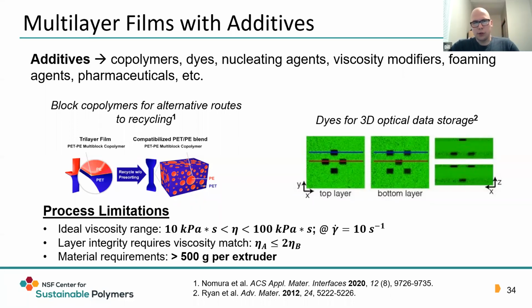Really, the only restrictions on the process are that you want your system to be in a viscosity range between 10 and 100 kilopascal seconds at this shear rate. That gives you good layer integrity if your viscosities are within 2 times of each other, giving consistent layer thickness throughout your whole system. But then again, you do have a high sample requirement here.